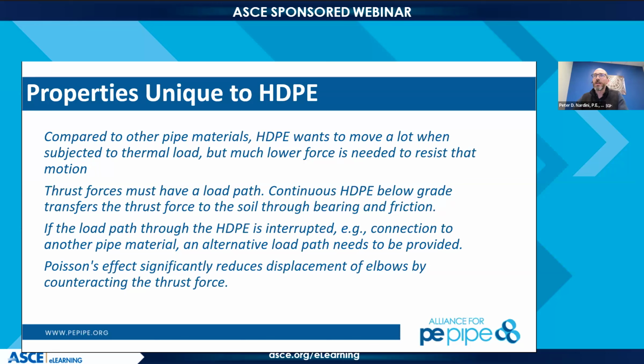And then in the middle here, when we think about longitudinal restraint of pipelines in general, we need to be really careful with these hydraulic thrust forces and make sure that we have a good load path. So when we're looking at HDPE, it's a continuous pipe material. We looked at the fusion connections, so the pipe is continuous. And when you're looking at a below grade application, the thrust forces in the pipeline are really transferred to the soil through bearing and through friction. If you're looking at above grade pipe, maybe you have to transfer those loads to some anchor supports. So we just need to be careful if there are any interruptions in that load path.